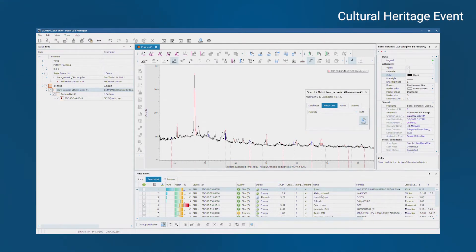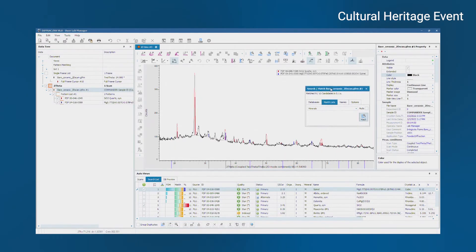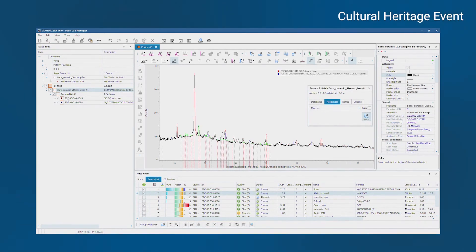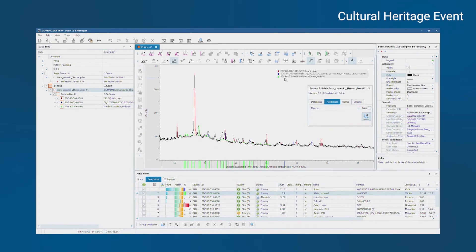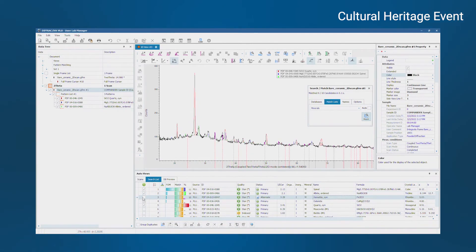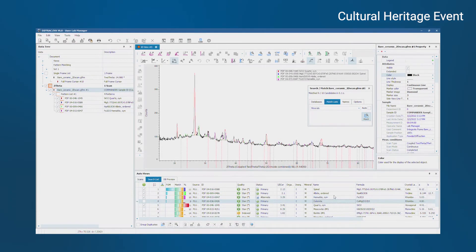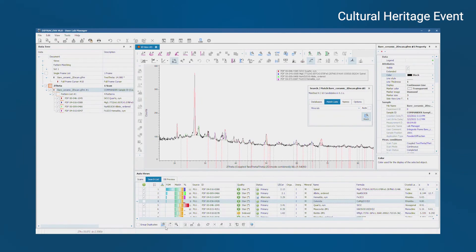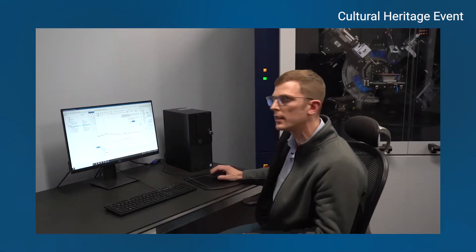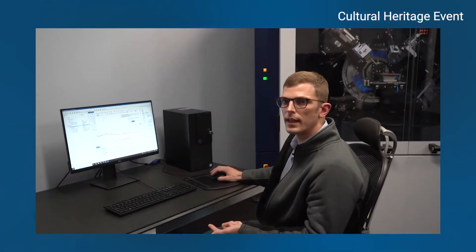And then we see we have maybe a spinel phase. Each of these phases that I think is a good match, I can check the box and it'll add it to the list. So then I can get a complete list of the phases that are present in this surrounding material. So here we have an albite, which is a feldspar. Next one on the list is hematite. Next one on the list is dolomite. This one doesn't really look like maybe it's a good match, so I won't select it. So this is how you can do phase ID, just taking a 2D X-ray pattern from a small spot.